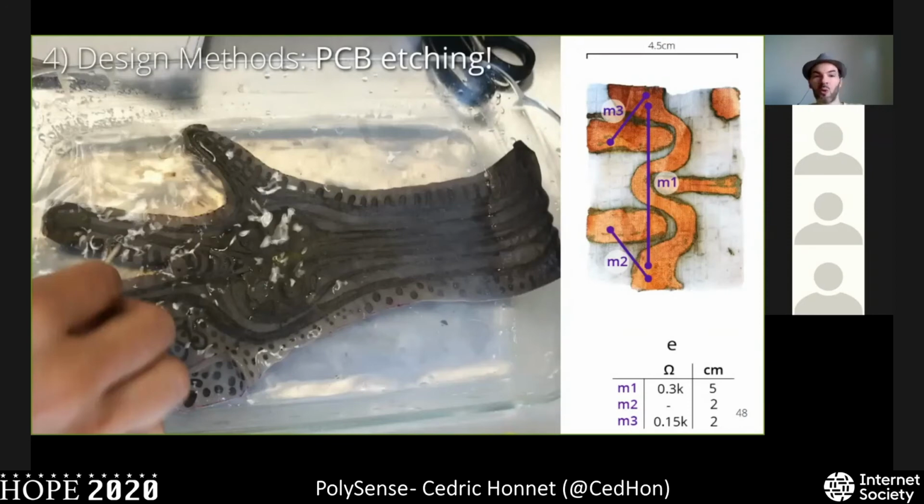But yes, so you always have to try a few samples at the beginning, and then you see what works, and you see how long each material needs. But usually it's something between 30 minutes and 45, 60 minutes. If it doesn't work after 60 minutes, it's unlikely that it will work. And you can see it visually. If you start from a white material, it should become almost black or dark gray.